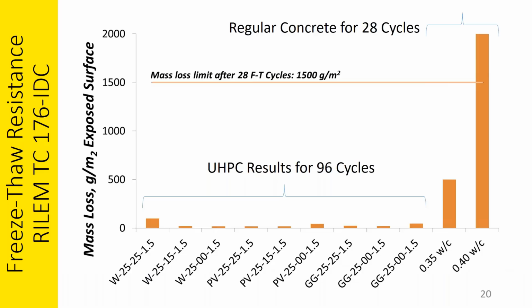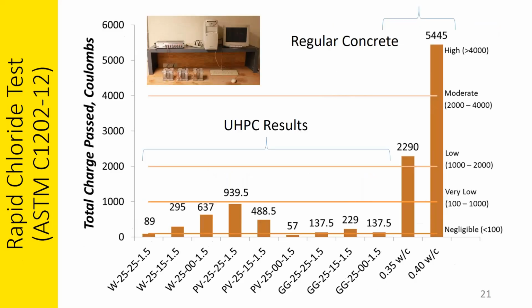And from some of our earlier research on UHPC, this is the freeze-thaw test under the RILEM method. On the right, you can see the performance of two different types of concrete. On the left are different mixes made from UHPC, and you can see that the performance is 2 orders of magnitude less mass loss compared to regular concrete. And that's why we think this material has such terrific durability properties. We tested it up to 96 cycles until we got kind of tired of testing it. These are expensive tests to conduct. They take many days to do, but others have tested it up to several hundred cycles, and again, with exceptional performance. This is another test that we did as well, many years ago.